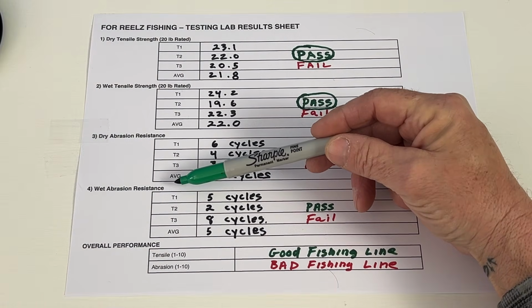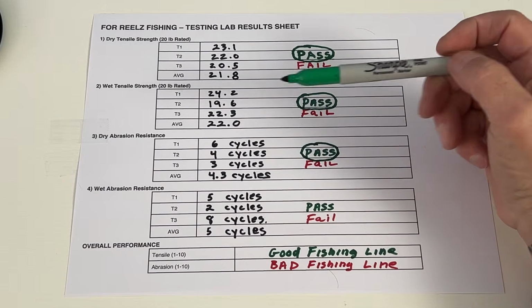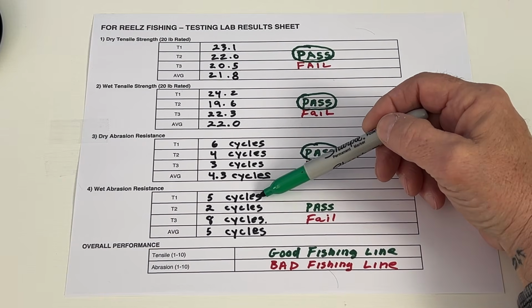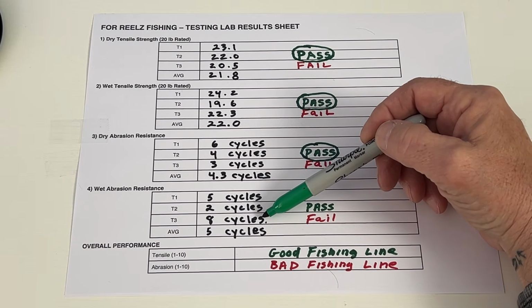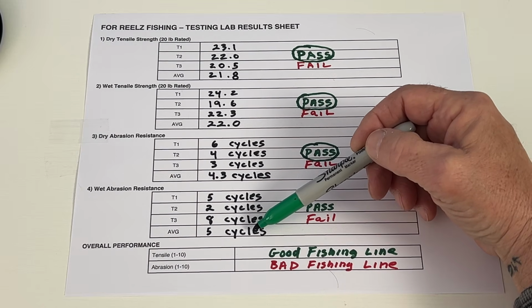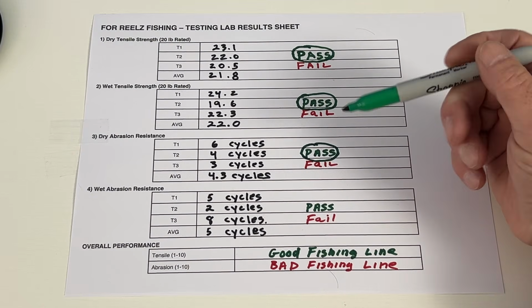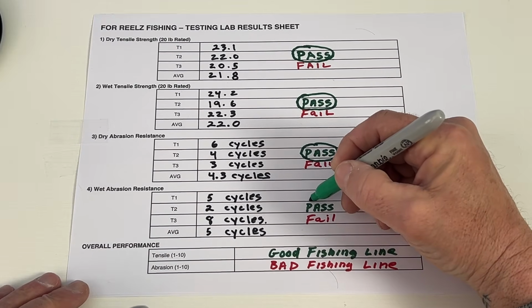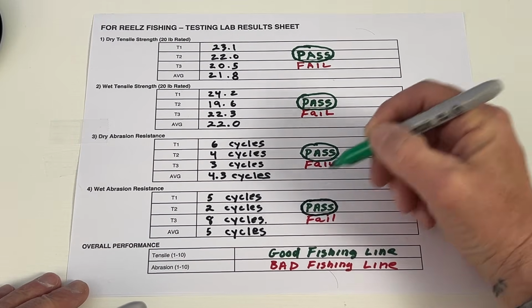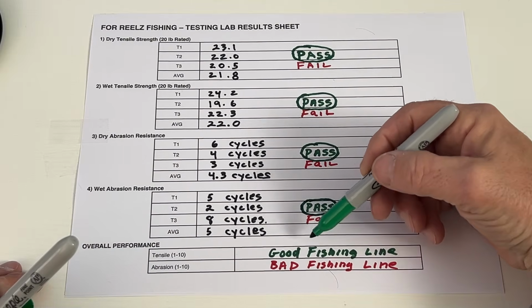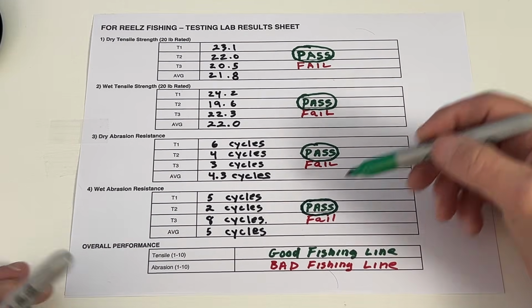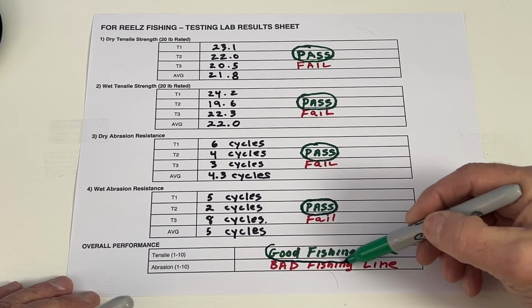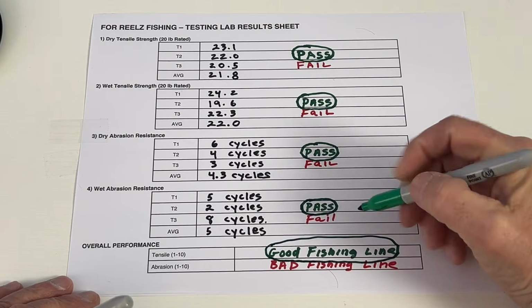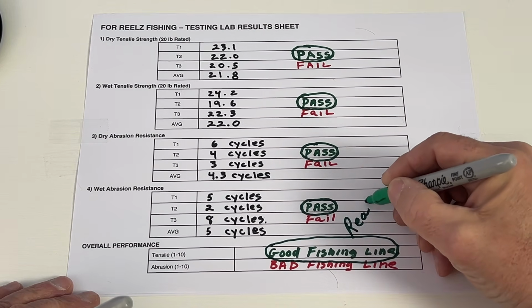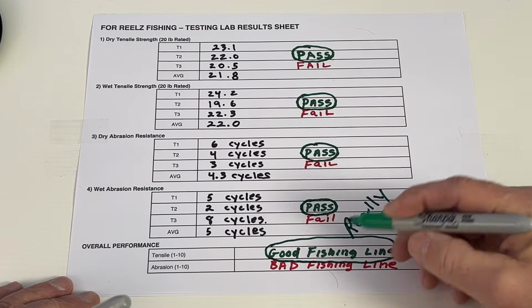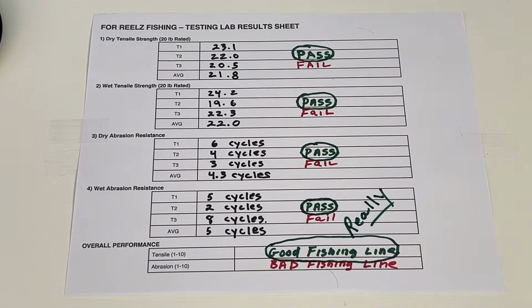Finally, we did the abrasion test on the wet braided fishing line that we soaked for 2 hours. Test 1 was 5 cycles, test 2 was 2 cycles, and test 3 was 8 cycles, for an average of 5 cycles. Once again, anything over 3 cycles is definitely a pass on this scale. So that's a pass. So finally, do I think this is good fishing line or bad fishing line? I think this is really good fishing line, and I think you can trust this fishing line.